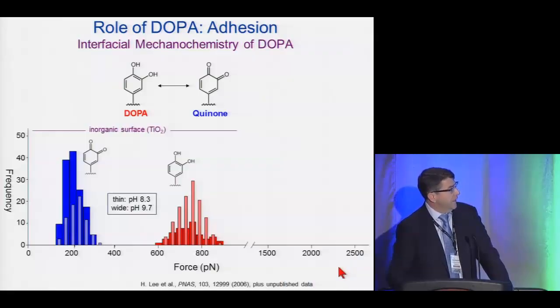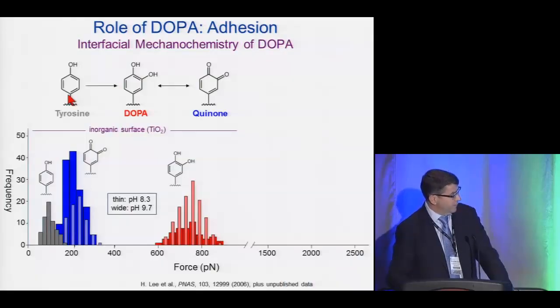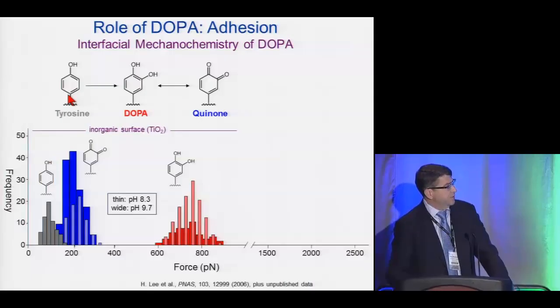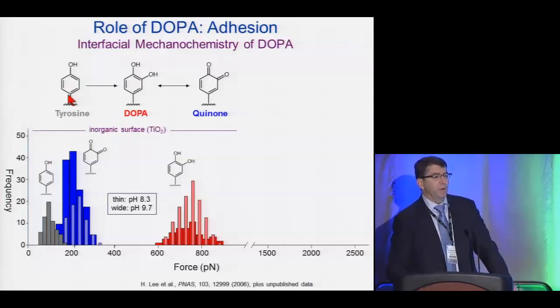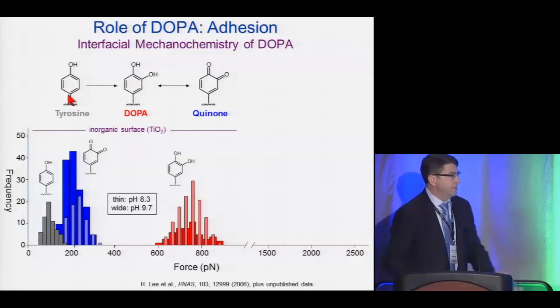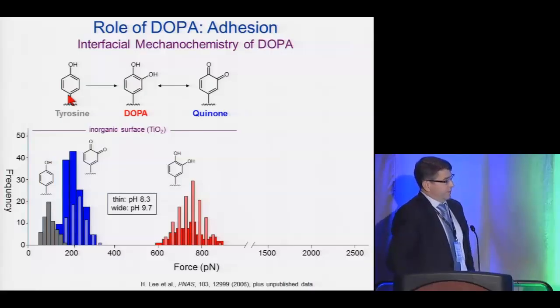Okay. Now, what about tyrosine? As I mentioned, DOPA is derived from tyrosine. So if you do the same experiment with tyrosine, you find a very low pull-off force. So this immediately tells us that the addition of the second hydroxyl group to form the catechol is very important and dramatically enhances the adhesion with the surface. Now, on TiO2 and most other inorganic surfaces, you might conclude from this data that the quinone is relatively uninteresting.